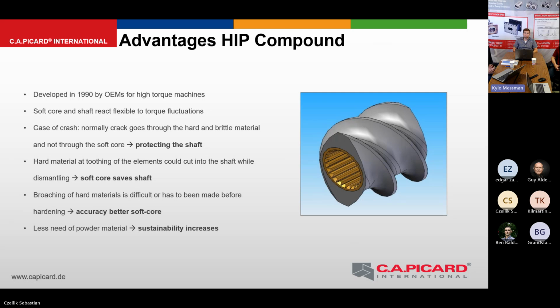And here are some points why we are using soft core and why we like to use soft core. So soft core elements were developed by the OEMs for high torque machines in the 1990s. So now it's over 30 years ago. And they have the advantage that the soft core and the shaft could react very flexible to torque fluctuations. That was the main reason why they were invented. And in the case of crash, if you have a through-hardened element, the crack normally goes really through the element and it will split up into parts. If you have a soft core, we see that the crack normally stops before the soft core, so you're protecting your shaft.